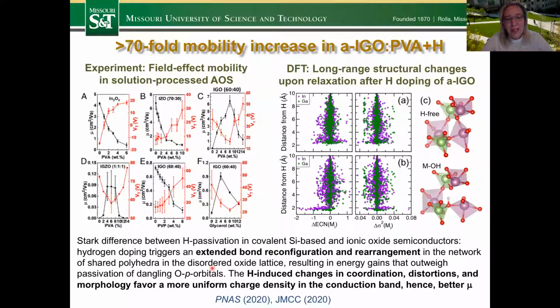Finally, these are very recent results, but very fascinating. This is again indium gallium oxide, with that high gallium concentration, 40% as I just showed, but it is hydrogen doped. What has been observed is that hydrogenation of these solution-processed amorphous oxides showed a 70-fold mobility increase, especially with gallium. Experimentally, they tried zinc and different gallium concentrations, and the effect is best with gallium: the more gallium we have, the higher the mobility increase.